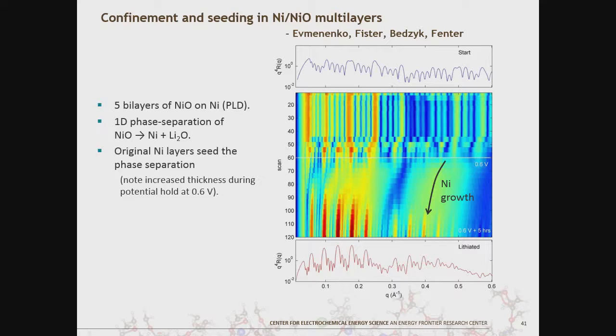And what's actually something that we've been looking at, but which I didn't mention - I think what's been more of a challenge than the electronic transport is, if you think about it, you have the lithium transport through these layers. There's some studies that Gena Evmenenko has done to actually look at one thin film with varying nickel thickness and find out - it turns out there seems to be a critical thickness below which the transport's relatively straightforward. So it's a little bit of a miracle that this actually works.